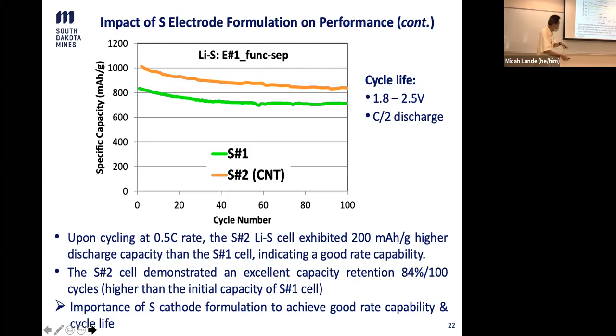And when we look at the cycle life again and compare S1 and S2, you can see that the S2 cell has almost 20% higher specific capacity throughout the cycle life. That tells us the rate is better. It delivers more capacity just by using a different cathode formulation. What we show here is that even just the cathode formulation is important to achieve good rate and cycle life.